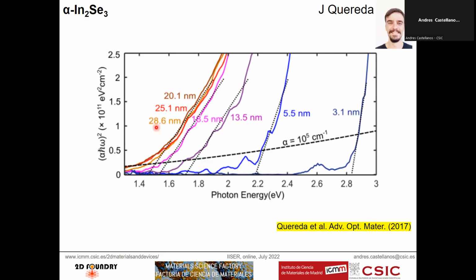Moreover, one of the things that makes this material interesting is that if you study the absorption spectrum, you see that the absorption band edge changes in energy a lot between flakes that are very thin and flakes that are getting thicker and thicker. Thick flakes have pretty small absorption band edge energies, while as you make this material thinner and thinner, the band gap becomes larger and larger. So you can tune all the way from 1.4 to 2.8, so it's a huge tunability.